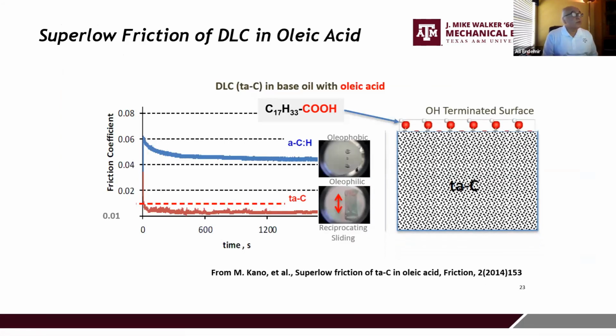Similar things could be achieved with these highly polar oil additives, one being oleic acid. This is a highly polar molecule, and if you put it with a base oil on the surface of the DLC—either hydrogenated or hydrogen-free—they tend to attach to the surface. With that attachment, the surface is again terminated with something more benign and less chemically active, and with that you could achieve extremely low friction coefficient, as shown in the red curve at the bottom.